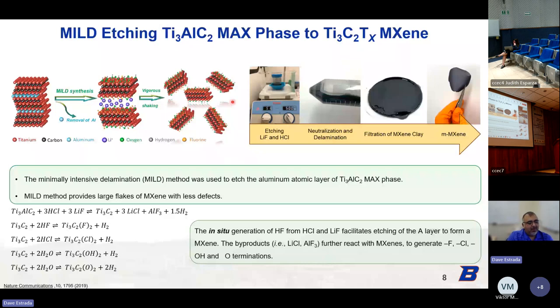We just do this over time. Once it's completely etched and neutralized, the MXenes are a really thick, viscous fluid, like clay. We put that on a Teflon dish, and then we can collect our MXene papers, which we can then redistribute into our different solvents to formulate inks. What's interesting with these is that during this etch process, you can get a lot of different surface functional groups because you have a lot of different reactions occurring.